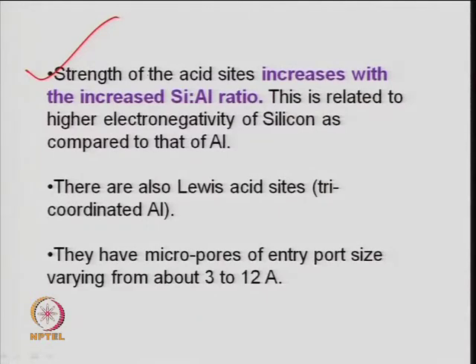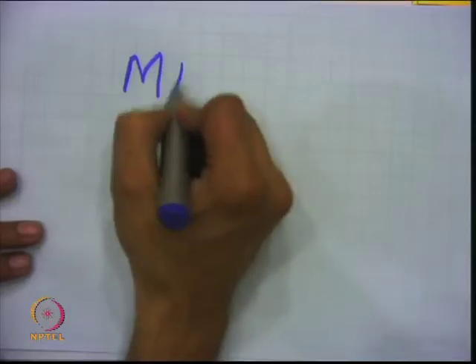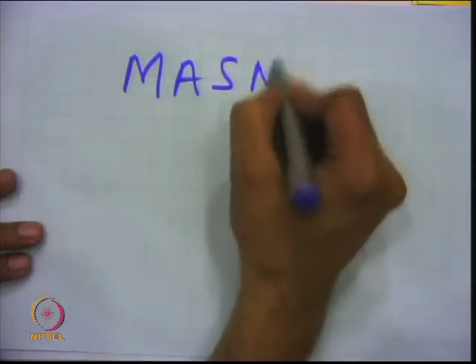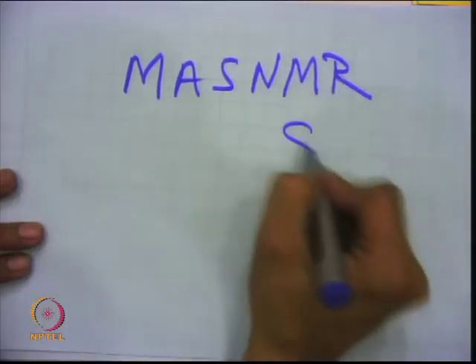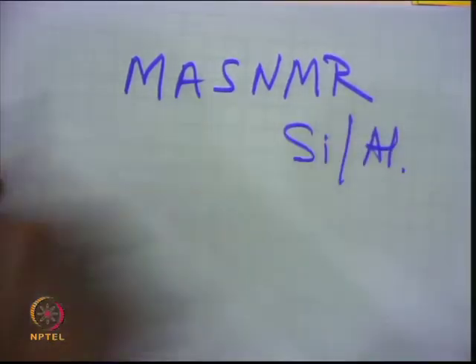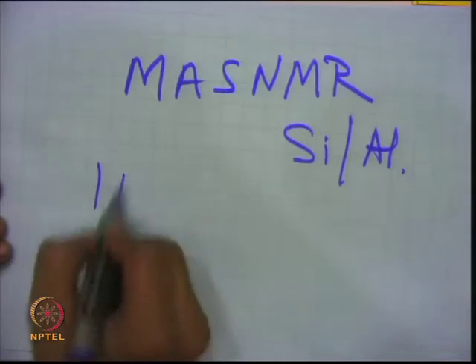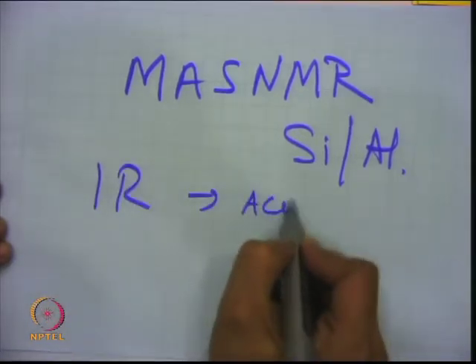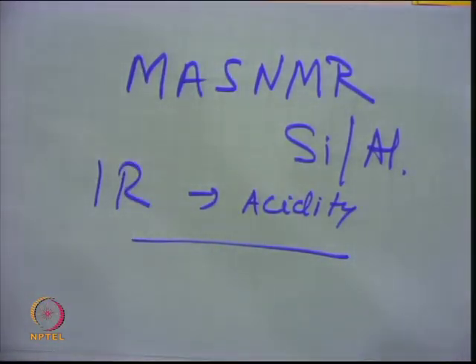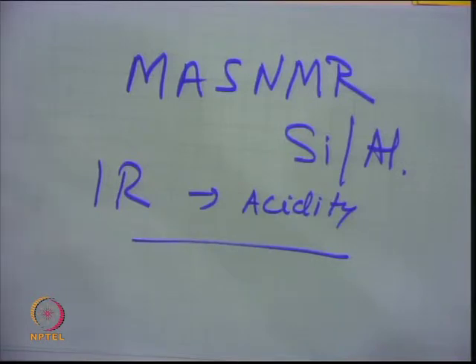Silicon-to-aluminum ratio in zeolite can also be characterized by solid-state NMR. These methods are generally used to characterize zeolite — NMR for silicon-to-aluminum ratio and IR with pyridine for acidity. The combination gives complete information about acid strength and type of sites (Brønsted vs. Lewis). There are also Lewis acid sites which are tri-coordinate Al³⁺ aluminum.